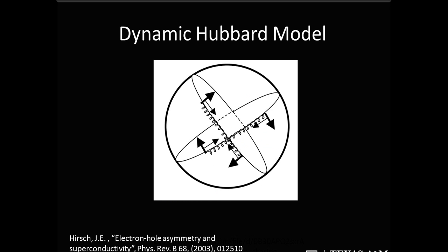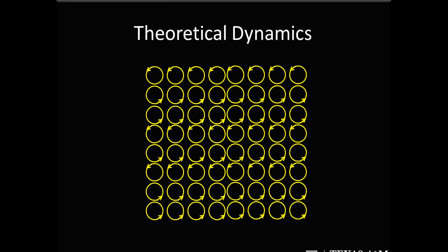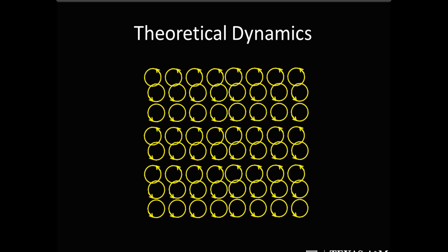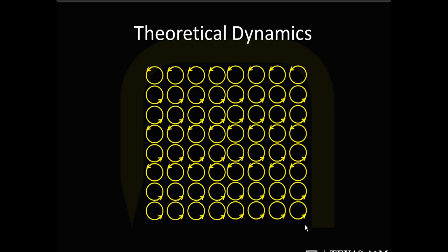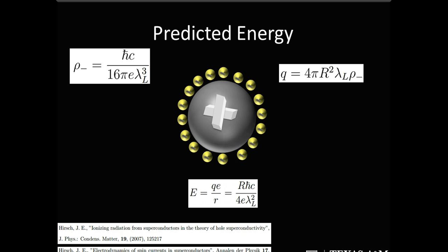And so now, at the end of the day, we have two opposite spin particles rotating around the center in opposite directions. So we have a net zero charge current, but a net positive spin current. Within the material, these spin currents cancel, but what that leaves is a net spin current along the surface of the material. It's that net spin current that we're going to talk about.